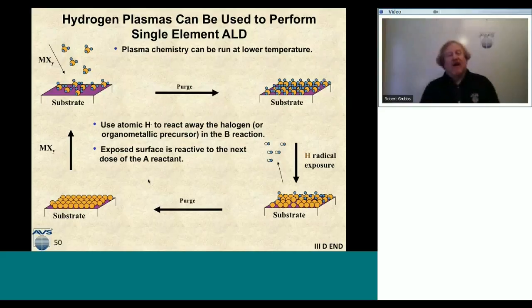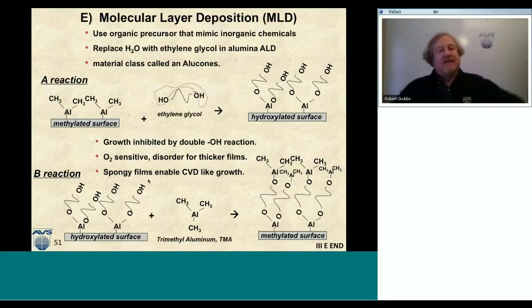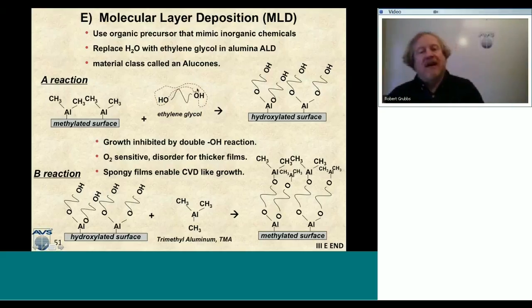And the last thing I want to talk about is molecular layer deposition, or MLD, and I just have a single slide on this. It's very exciting because it's a combination of inorganic chemistry and organic chemistry. Instead of using water as my oxidant source for ALD, I'm going to use an organic molecule. One example is ethylene glycol. You'll notice that we have two OHs on either end of this molecule, and what I have circled here in red is an H, two H's and an O. So this molecule can essentially react like water, but it has these carbon chains between it.